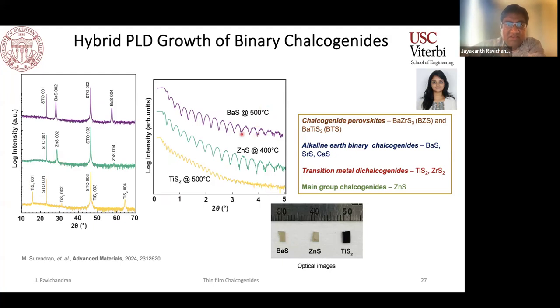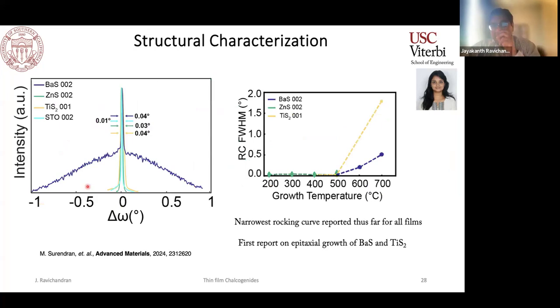You don't have to go as high as 700 C, and you can still get nice reflectivity, thickness oscillations in X-ray reflectivity and texture. So this made us pretty confident that something is getting better with this technique. When we started looking at the rocking curve, what we noticed was that in general, the rocking curves are pretty narrow below, say, 500 degrees Celsius, but as you go to higher and higher temperatures, there seems to be a lot of island formation and then roughening, which leads to much poorer coherency in the rocking curve itself. But overall, it seemed like the rocking curve is reasonably narrow, given that these are highly heteroepitaxial thin films that we are growing on pretty much incompatible substrates, because there are no commercially available high quality substrates for many of these materials.